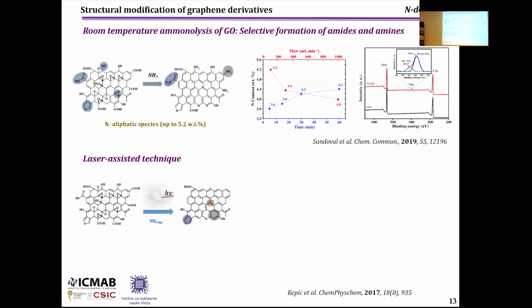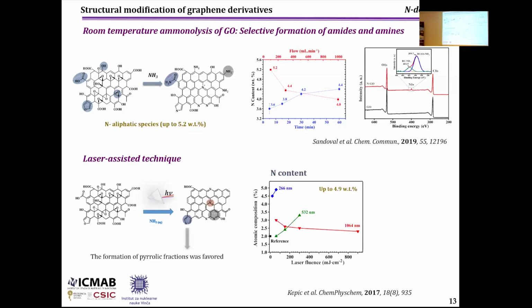laser-assisted technique was developed in collaboration with Ángel Pérez. In this case, we use a laser-assisted technique to synthesize strictly doped systems. We use different lasers with different fluence and also obtain up to 5% of nitrogen in the structure, but in this case the formation of the pyrrolic fraction was favored. This way, we are able to tune the properties of the materials by selecting the group we are introducing into the structure. These two approaches are simple, fast, low cost, and efficient.